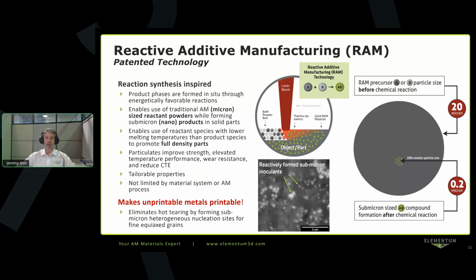So the approach that we are using extensively at Elementum 3D and that we've patented, we've termed reactive additive manufacturing, also known as RAM. And this is inspired by reaction synthesis. Reaction synthesis is forming product phases from in situ reactions that are energetically favorable from reactant phases. This enables the use of traditional AM micron scale reactant powders while forming submicron or nanoscale product phases in the solid parts. Ideally you want your inoculants to be nanoscale, but working with nano-sized powders isn't always very friendly.